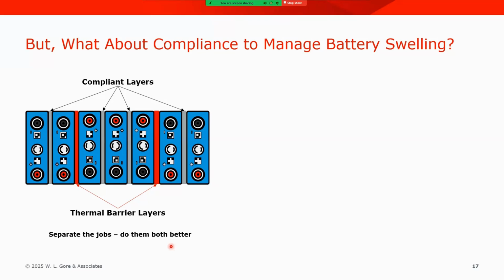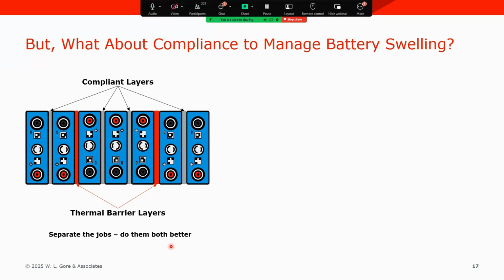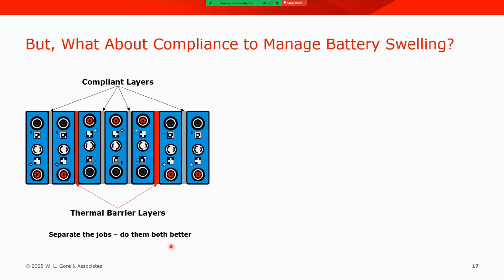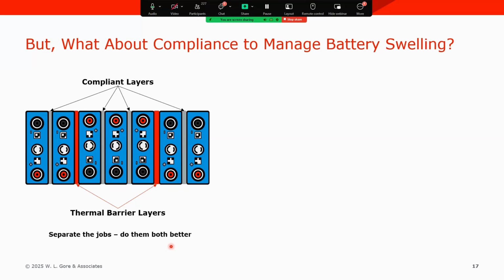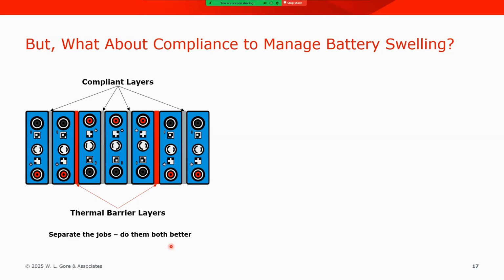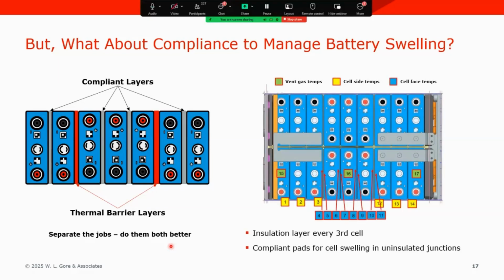We're also investigating the potential for making heterogeneous laminates, which would include a thin layer of GORE battery insulation laminated directly to a compliant layer or a compression pad layer. And with that in mind, we have a variety of different options to again address both jobs, separate them, and do them both better. But this first example of putting compliant layers in alternate junctions has actually been tested in the field in a mini module test by one of our early testing partners. And here's the schematic for that experiment.